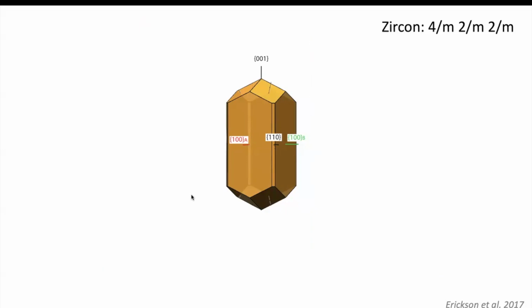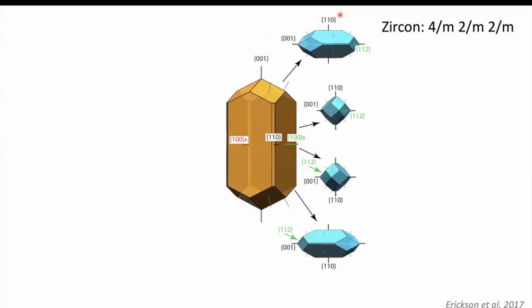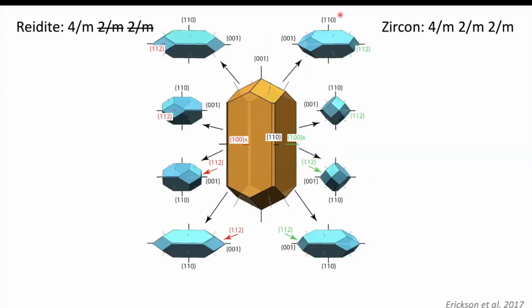When zircon transforms to reidite at high pressure, the 001 of zircon, that's this long C-axis, is aligned with the 110, those skinny side faces of reidite. And this can happen in 8 different ways because reidite has lower symmetry than zircon. They're both tetragonal, but zircon is the same up and down on the C-axis. Reidite is not, because it's missing this other symmetry.